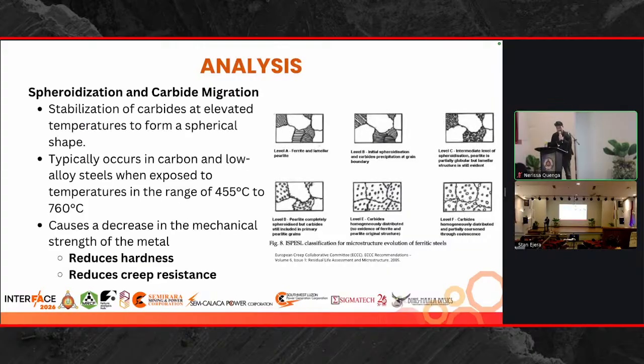spheroidized carbide. So these spheroidized particles or carbides eventually disperse on the microstructure and result in a loss in mechanical properties, particularly hardness. So this spheroidization makes the component softer than it is expected. So it also causes a reduction in creep resistance, which I have mentioned earlier, which again is detrimental in high energy components.